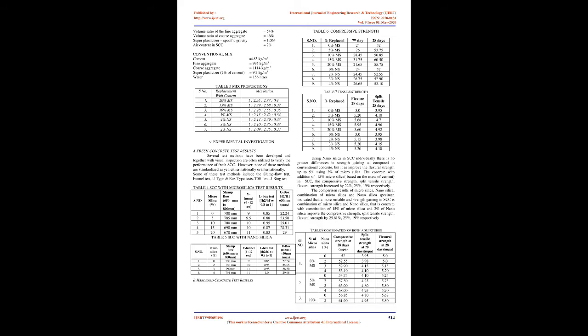A maximum of 8% of limestone powder with silica fume, 30% of quarry dust and 14% of clinkers was able to be used as mineral admixtures without affecting the self-compactability. The silica fume was observed to improve the mechanical properties of SCC, while limestone powder along with quarry dust affected the mechanical properties of SCC.